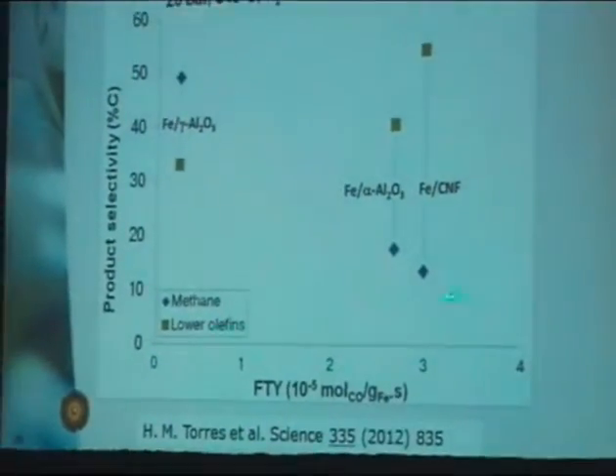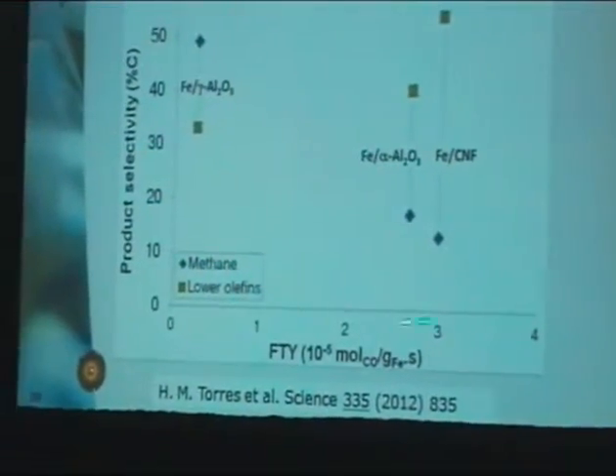Well, the support effect in one plot: if we have the product selectivity, our enemy is methane, because we operate, in this case, at 340 degrees centigrade, 20 bar, and a hydrogen/CO ratio of 1. Very severe conditions and very high CO conversions for these active catalysts. The product selectivity as a function of the catalyst activity per gram of iron. With this conventional support, our problem is twofold. We have low activity and we make lots of methane.